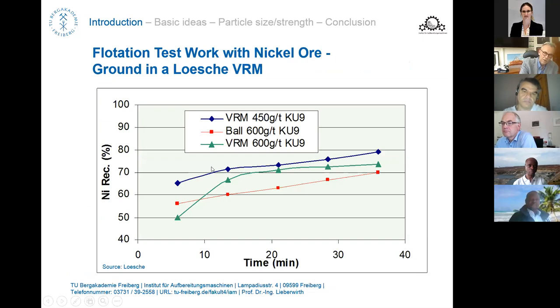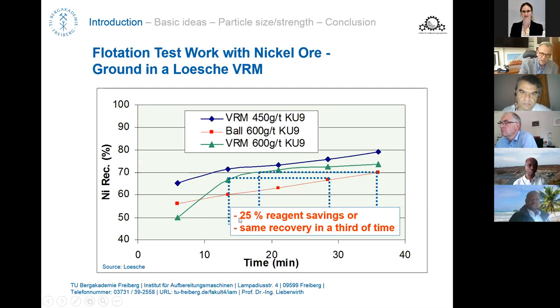And the other thing which we could also show with these ores which we investigated, but this is another scheme I have found here for nickel recovery: you can also show an increased recovery by flotation if you go with dry grinding. Dry grinding obviously has advantages since the surfaces of the particles are not spoiled by the slurry so much, and therefore you can see increased recoveries. Another point which speaks in favor of dry grinding, here in this particular case, is that 25% reagent savings was reported, or the same recovery in a shorter time, which might also be interesting.